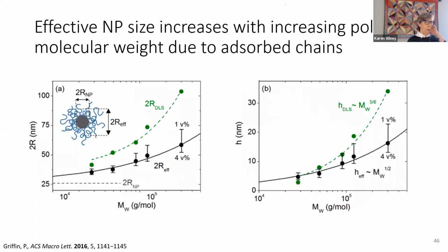And this is pretty easy to understand because we know we have an adsorbed layer. So we can calculate from the diffusion coefficient what the effective size is, right? And then we also have from DLS. Now DLS is in a solvent, so the chain will be much more swollen. This is in the melt state from the diffusion coefficient. And we see that this increases with molecular weight, which makes sense because this is now the thickness of this adsorbed layer, and the thickness of the adsorbed layer in the melt is increasing as molecular weight to the 1/2. So it's increasing the same way as Rg would increase with molecular weight. And so,